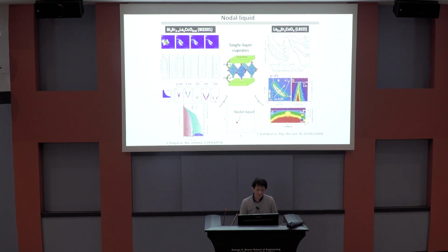This lightly doped state was also studied in single layer cuprate, for example bismuth-2201 and LSCO. In bismuth-2201, again, the quasi-particle peak appears only when doped more than 10%. If you go around the edge of the TC dome, you can observe only a single point with a quasi-particle peak.